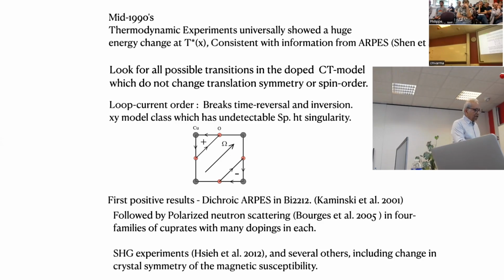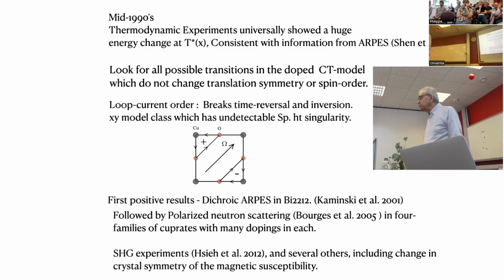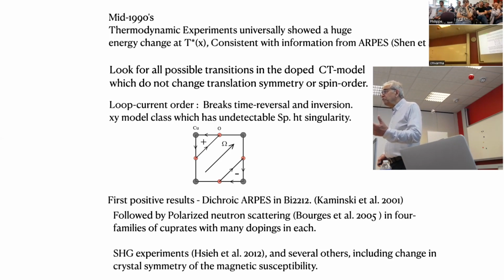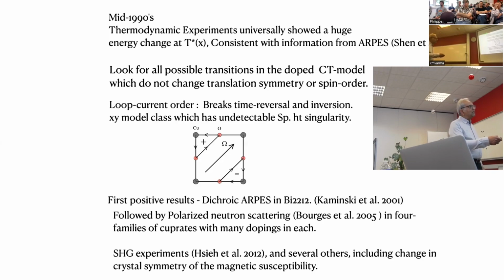So I shall briefly describe, if people are interested, the physics of this loop current order which I proposed, and it was proposed to be something which would not have been detected by then. It would be a hard phase to detect. And also, I needed a phase where there's a phase transition without a singularity in the specific heat. Okay? And this is one such thing in two dimensions. So this is a phase in which on the copper oxygen unit cell, there'll be a spontaneously developed flux, here positive and negative in each unit cell, so that you could define a magnetoelectric or anapole order parameter, which is magnetization at a point R crossed with the vector R.